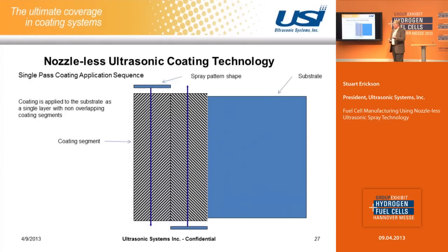So an example of a single pass coating recipe: if you had a spray pattern that was 100 millimeters wide, you would apply a coating every 100 millimeters. And that's a way to do it. We typically don't do that, but that's a way of applying coating to a substrate.